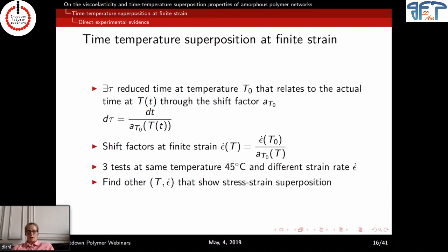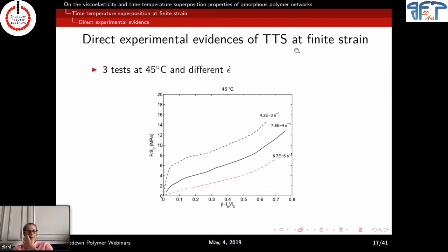So to try that, we set 3 uniaxial tension tests at large strain, temperature 45 degrees, and different strain rates. We measured the response and tried to find other couples of temperature and strain rate that show the same stress strain response, so a superimposition of the stress strain responses. Okay, so at 45 degrees, we have 3 responses. Basically here it's close to a rubbery state, and we are applying higher strain rate to get responses that are more of the viscoelastic regime stress strain response.